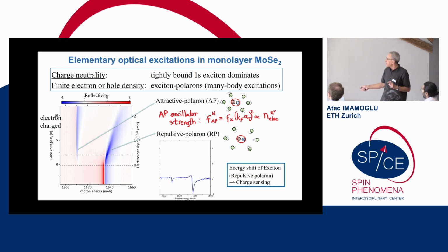Now, what will be of interest to us is what we refer to as the attractive polaron resonance. The reason is that its strength, and we can show this exactly for low densities, is given by the exciton oscillator strength times the Fermi momentum times the size of the exciton squared, and this is directly proportional to the electron density in the opposite valley. Therefore, by measuring the polarization selective strength of this resonance, we can determine the electron density in the opposite valley.